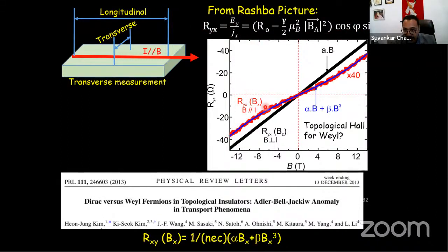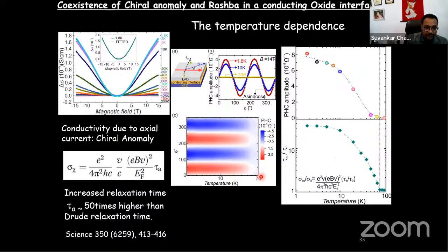But this is our Hall data when you measure in the I parallel B configuration of the applied magnetic field, which has a B linear plus B cubic dependence. It was reported long back for a Weyl fermion system in 3D-like materials, where one could expect to see B linear plus B cubic behavior. So this gives us a hint that we might be looking into some Weyl type physics in our system.